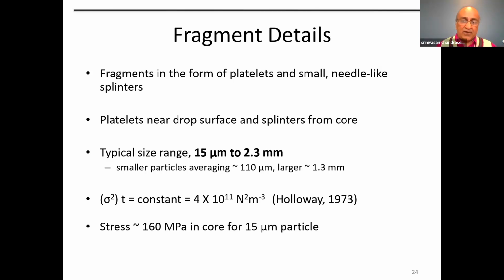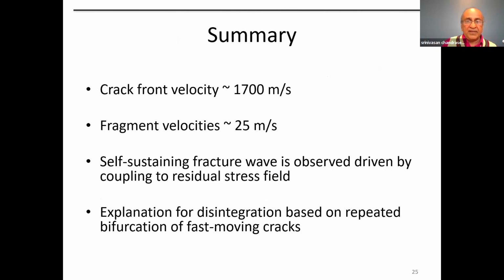One of these is called Physical Properties of Glass by Holloway. It's a wonderful book and tells you all about glass. And he gives this formula. From the fragment sizes, you can get an estimate of the stress, which is about 160 megapascal. It's not important what that is. That's the stress in the core of the drop. We didn't have measurements at that time, but subsequently I'm going to show you some measurements.